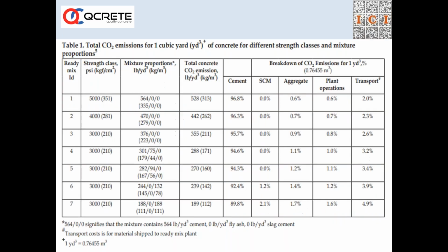So what are the carbon dioxide reductions that are possible if we are using SCMs? Take a 335 kg mix with 0 kg of fly ash or 0 kg of GGBS. In this, the carbon dioxide emission is 313 kg per cubic meter.